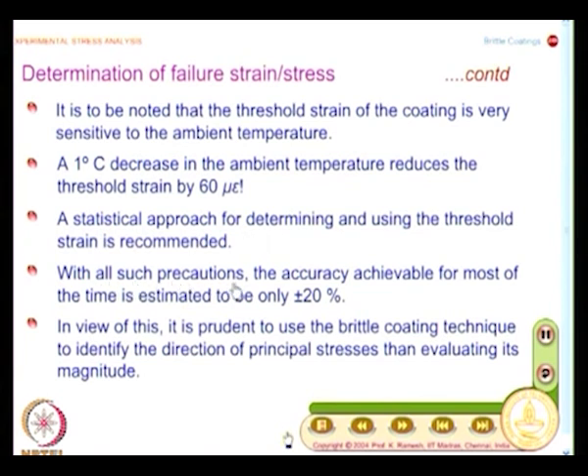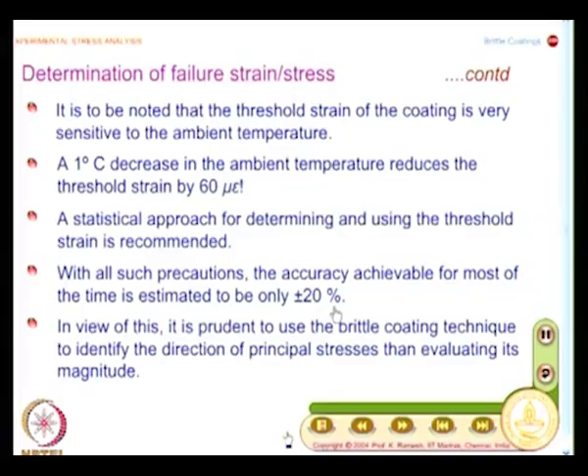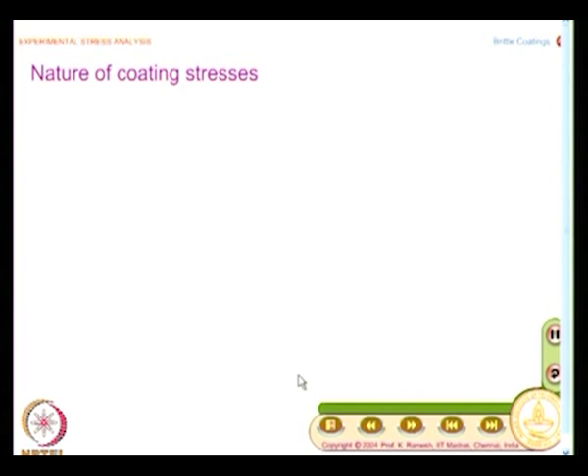Even with all such precautions, the accuracy achievable most of the time is estimated to be only plus or minus 20%. This is more of a caution. You have to keep in mind that with all the precautions you take, you cannot get an accuracy better than plus or minus 20%. That is the reason I have always been saying that when you use a brittle coating test, use it more for finding the principal stress direction, thereby reducing one strain gauge per point. To establish that, I am showing you all this. Even a 1 degree centigrade change can affect the failure strain by 60 microstrain, so the quantitative evaluation becomes involved as well as not very accurate.